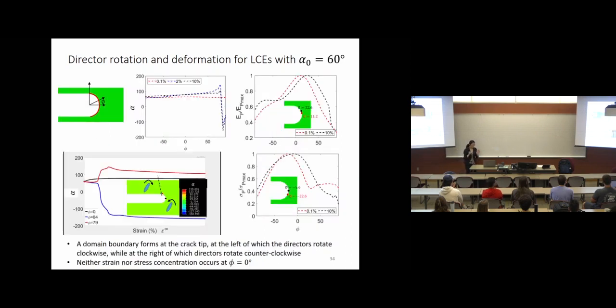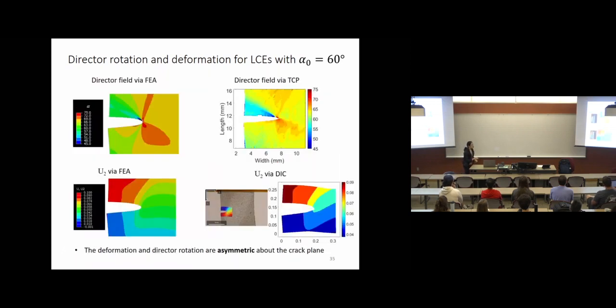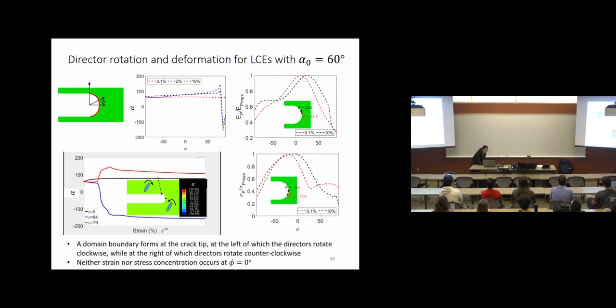Next, I'm showing you the result when the director is at 60 degrees. Therefore, you have a liquid crystal elastomer film, and the director is in this tilted direction, 60 degrees with respect to the x-axis, and we are stretching in this 90 degree direction. Let me show you the result here. Again, I'm plotting the director evolution as a function of strain for three different initial phi angles, corresponding to the three points here.